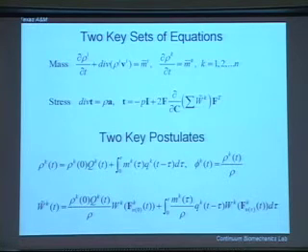We know that vascular collagen under normal conditions has a half-life of about 70 days. In hypertension, that half-life will reduce to 7 days. So it can be rapid turnover in hypertension. We also know that under normal conditions, vascular elastin has a half-life on the order of decades. So this Q will account for how rapidly the original material will actually degrade, and that will increase in cases of disease.